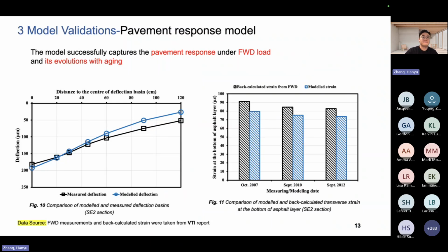The final part of model validations is for the pavement response model. Here I use the FWD measurements and their back-calculated strain as the benchmark. So we see that the model can capture the pavement response under the FWD load, and it also captures the response evolutions with the aging.